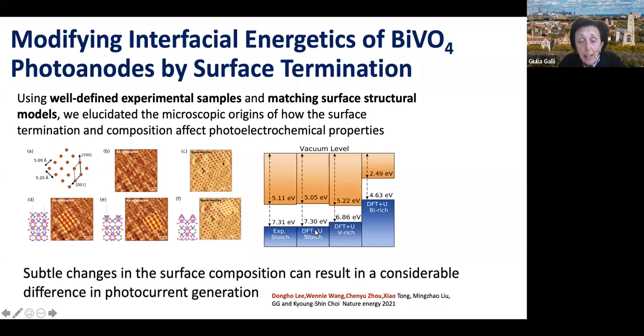Note that the level of theory here for this calculation, for many, many surfaces, is not the greatest, not the highest. It is DFT plus U. Why? Because we could not do so many surfaces with just a hybrid functional. So we checked that the trend would be okay, and we established with a certain number of comparisons that the trend as a function of surface termination would be okay. And then we did many calculations with DFT plus U, and we determined U by comparing again with experiment.